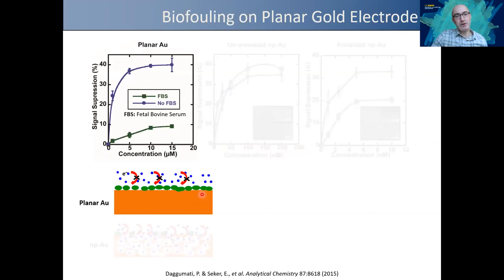If you have a planar gold electrode that you are trying to detect DNA with, if it's in phosphate buffer, it works perfectly. You have very high signal. But if you put it in fetal bovine serum, the surface is fouled with the serum molecules, albumin mainly probably, and it blocks the charge transfer and you cannot detect anything. The signal is really low.